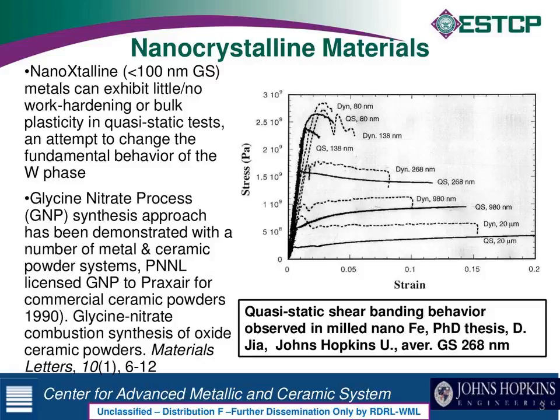But the approach we were looking at with Battelle was to look at some synthesis type processes. We looked at both a freeze-drying process and a glycine nitrate process, which is ultimately the one we spent the most time on. It looked like it had the most promise. Battelle had a lot of experience with that. They had patents on producing metal and ceramic powders using this glycine nitrate combustion synthesis process. And as we'll see, we have a patented application that came out of this work also for metals. So that's very quickly a background in terms of why we were taking this approach.